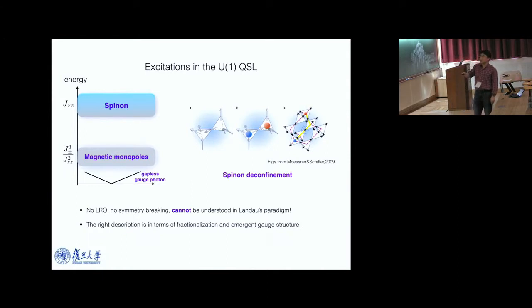But in this U(1) spin liquid phase, the spinons are deconfined, because all the spins along the pathway are strongly fluctuating. It costs only a finite amount of energy to separate these spinons to arbitrary distance. These are the spinons, this is the gauge photon, and this is another particle called a magnetic monopole. Some people call it the electric monopole, because there's confusion in the terminology in our field, so I will stick to the name magnetic monopole. This is very different from the spinons. A spinon has a classical analog, a defect tetrahedron, but a magnetic monopole does not.